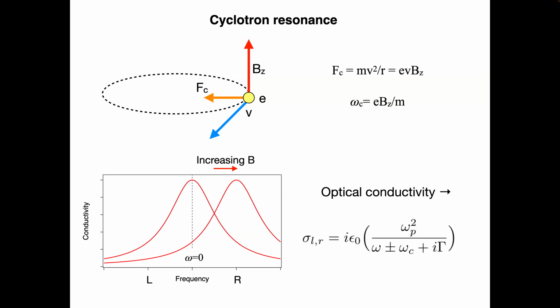When we're putting materials in magnetic field, we like to plot the data as a function of the response to right and left circularly polarized light. And we do that by plotting it as positive and negative frequencies. And that makes sense: if right is e to the i omega t, left is e to minus i omega t. One of the reasons we like that is that the form in the right and left coordinate frame is just super simple. It's just the normal Drude expression where the pole, which at zero field is sitting at zero frequency, is just shifted by the cyclotron frequency. So you can just, by eyeball on the data, pick out how this peak shifts.